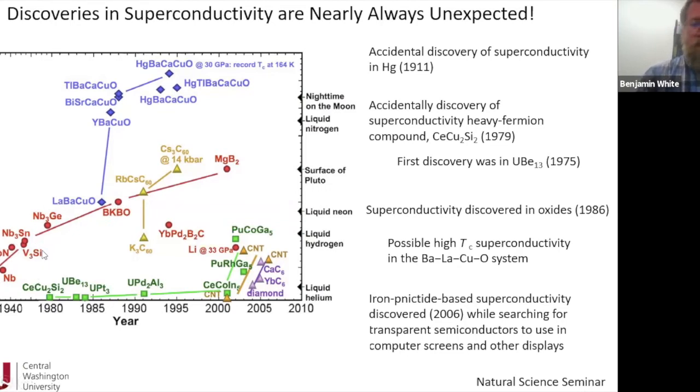And Matthias was mainly working on these types of superconductors. His empirical rules of thumb included things like, you don't look at oxides, only look at intermetallic compounds. You don't look at materials that have a magnetic order to them, especially ferromagnetic. In general, you just shouldn't look at materials that have magnetic moments at all. And so these rules of thumb guided a lot of the research and also led to a lot of surprises,